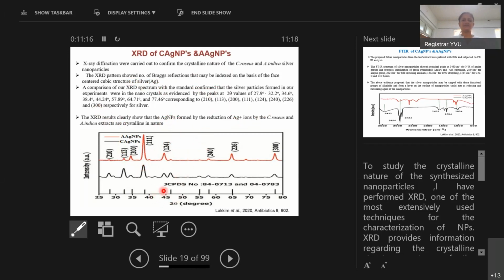These nanocrystals show peaks at 2 theta values of 27.9 degrees, 32.2 degrees, 34.6 degrees, 38.4 degrees, 44.24 degrees, 57.89 degrees, 64.71 and 77.46 degrees, corresponding to the planes 210, 113, 200, 111, 124, 240, 226 and 300 respectively for silver.